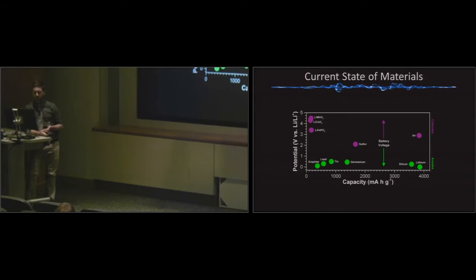And so as we start getting into the higher capacity cathode materials like sulfur and air, you can see that their potential is a little bit lower, and so that means our overall battery voltage will be a little bit lower. It turns out that doesn't really matter as much because when you look at energy density, that's your capacity times your voltage. And so even though we cut the voltage in half, by about 2, we're still increasing the capacity by a factor of almost 10. And so when you multiply those two numbers together, you still get a massive increase in energy density.